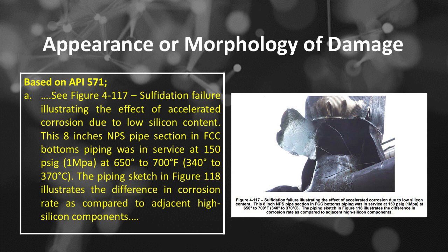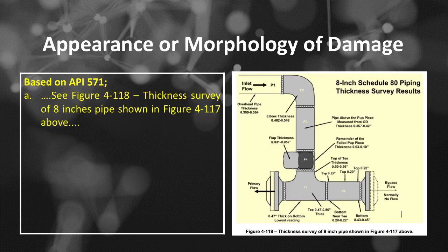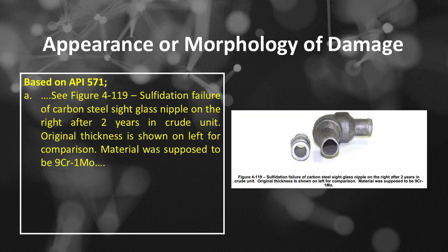This 8 inch NPS pipe section in FCC bottoms piping was in service at 150 psig or 1 MPa at 650 to 700 degrees Fahrenheit or 340 to 370 degrees Celsius. The piping sketch in Figure 118 illustrates the difference in corrosion rate as compared to adjacent high silicon components. See Figure 4-118, thickness survey of the 8 inch pipe shown in Figure 4-117 above.